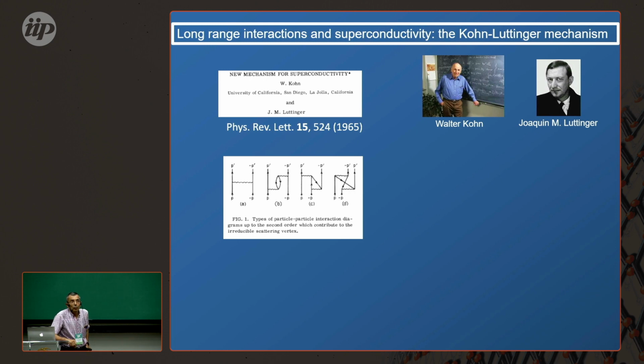As I said, the seminal work on superconductivity arising from repulsive interactions was proposed way back by Walter Kohn and Joaquin Luttinger. They realized that in a metal you have a sharp Fermi surface, and when you screen a repulsive interaction, you create Friedel oscillations, and these Friedel oscillations in real space lead to regions where the potential becomes attractive.